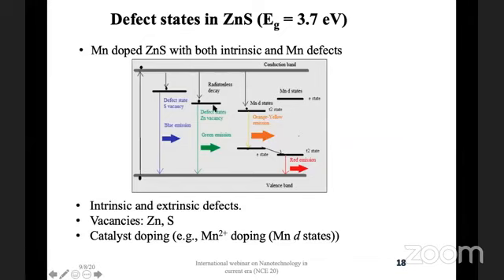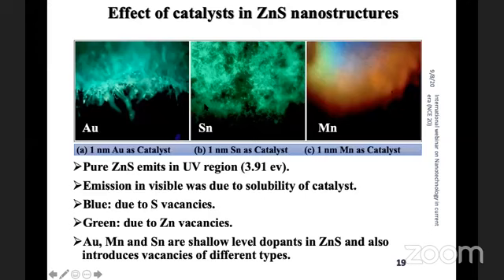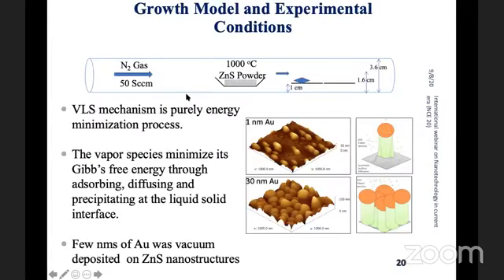Now these, particularly the green and the orange-yellow, fall in the plasmon resonance energy of gold. This is just to demonstrate that if we dope zinc sulfide nanostructures with different materials, with gold, tin, or manganese, we get different colors as well. In the case of manganese, we get rainbow colors, the whole range of colors. In the case of tin, we also get mostly green colors, but to a certain extent, we can get blue color as well. So that's very important. And if we change the size of the film we deposited for the VLS process, we can change this color combination as well.